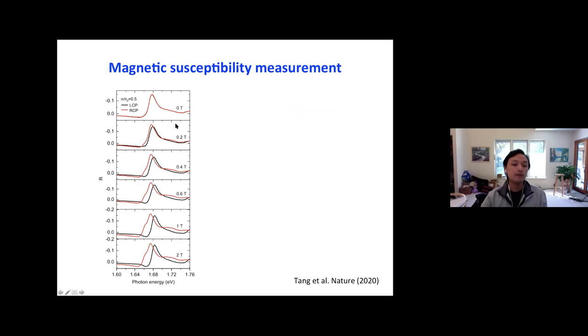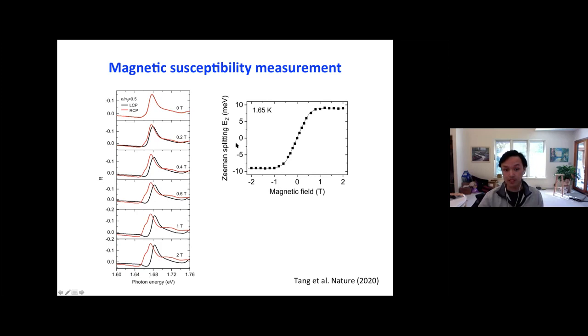Well, now if you increase the magnetic field, then you can clearly see a Zeeman splitting in the exciton resonance, which is this peak here, between the left and right-handed channels. And you can trace the peak energy, or the splitting of the peak energy, for left and right-handed light as a function of the magnetic field, which is the Zeeman splitting of the exciton. It looks something like this. It's linear near zero Tesla, but it quickly saturates for magnetic field above 1 Tesla. It really is reflecting that the local moments in the system are easily polarized by a magnetic field on the order of 1 Tesla. Okay.